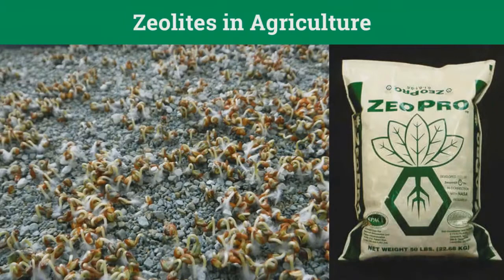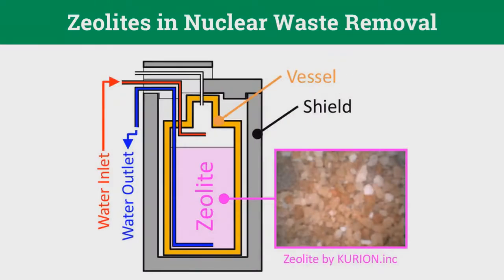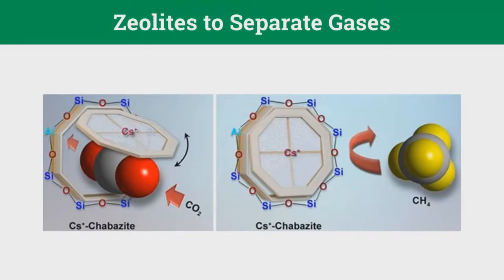There are many uses of zeolite which exploit the ion exchange capabilities of the mineral. Zeolites are used in soil conditioning, which increases fertilizer efficiency due to the zeolite's molecular sieve properties. Zeoponics is a new method of plant growth which uses artificial soil with zeolites as a major component. The selectivity of clinoptilolite for certain heavy metals is the principle behind many water and waste treatment plants. Zeolites rapidly take up and release water and exchange sodium and calcium, making them useful as drying agents and to soften hard water. The cesium-137 from contaminated waters after the Chernobyl accident was removed with the help of zeolites. Zeolites like Phillipsite and Mordenite can also separate gases; in the USA, chabazite is used to separate CO₂ from methane in landfill sites, and natural ferrierite is used to remove elemental sulfur from gas streams.